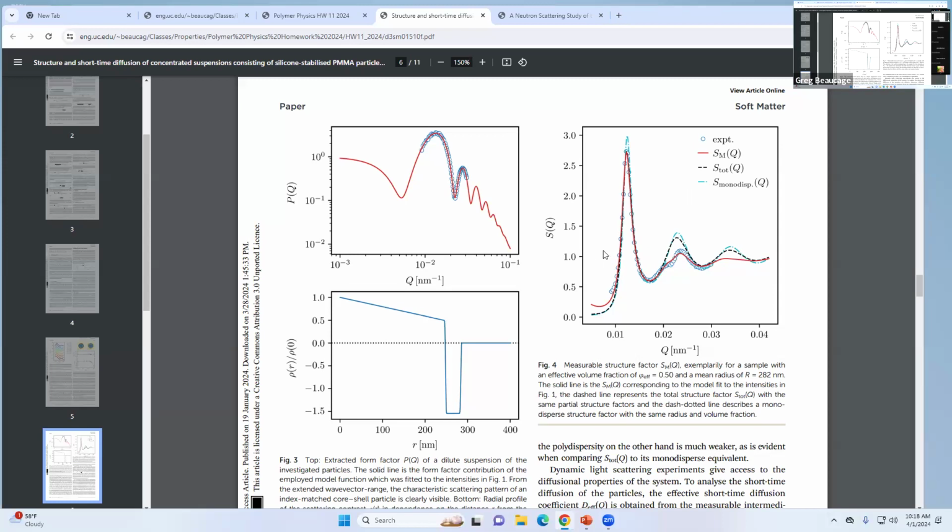It describes the organization of things, but it isn't exact. Two things that were different could give the same correlation function, put it that way. It's only a scalar quantity, so you can't give a 3D mapping of the thing exactly. It's kind of odd that this isn't actually giving you the structure.